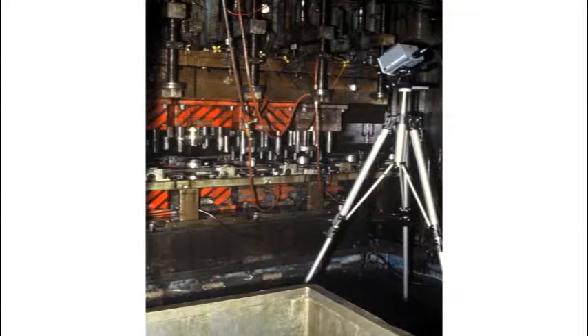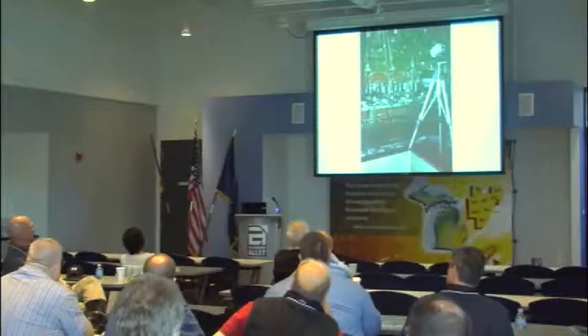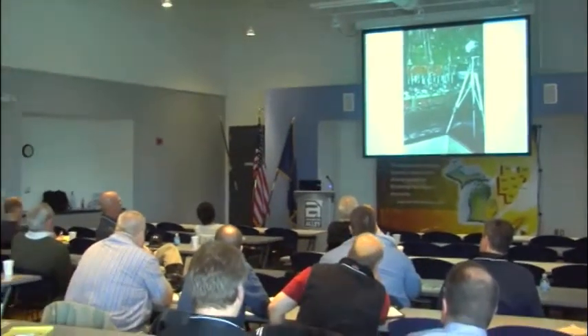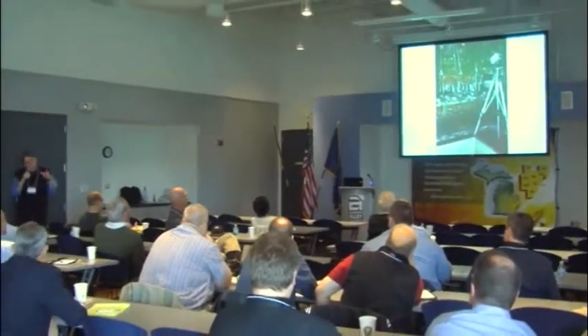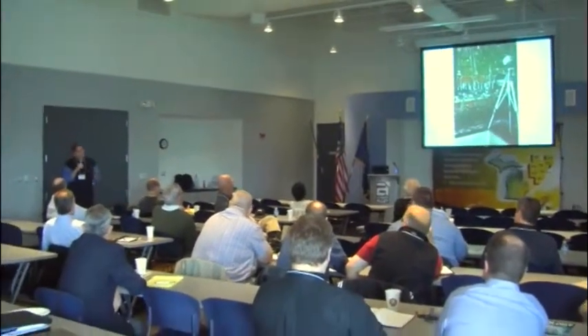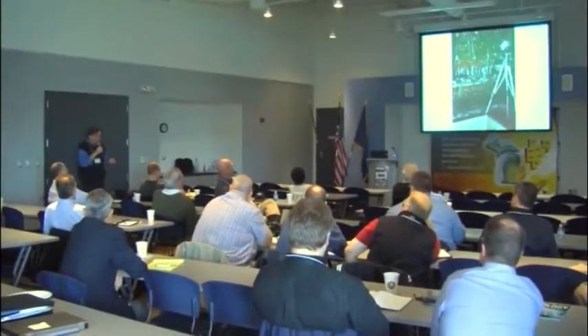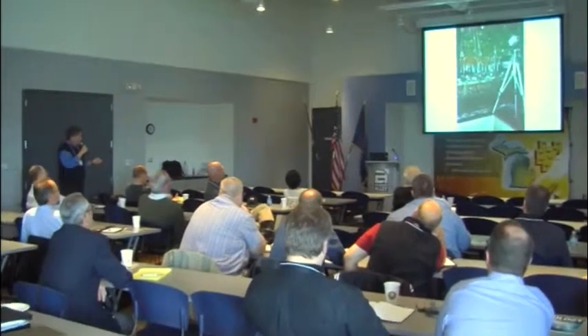I got the call. What's that surface reaching during the deep draw? What's that oil have to meet spec-wise? So I set up, I'm looking at all the different die draws that they're doing, getting a temperature during the draw process. A nicely thick coated oil shiny surface becomes a fairly good emitter, and we can make a measurement on that.